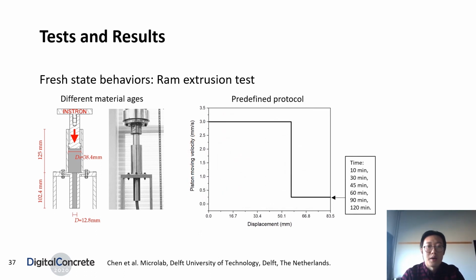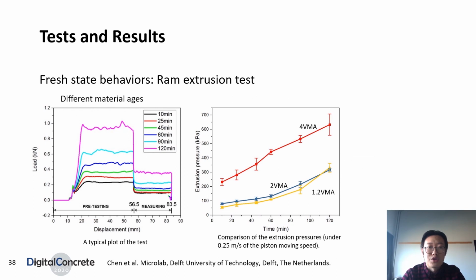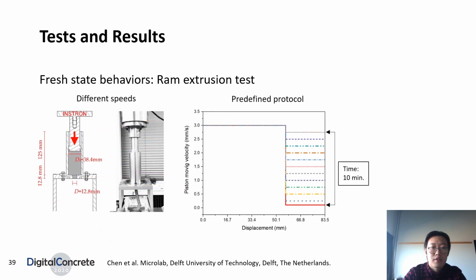For the time-dependent property, a predefined protocol is applied at different material ages to obtain the corresponding RAM extrusion pressure. Increasing VMA dosage could increase the extrusion pressure, especially for the mixture with the highest VMA dosage. It shows an extremely high extrusion pressure even at a very early age. For different extrusion speeds, the material was only tested at the age of 10 minutes.